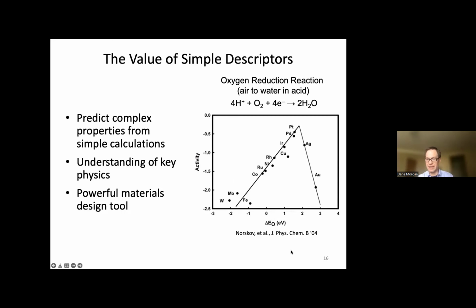So here, for example, is a classic descriptor approach that was pioneered by Jens Norskov about 20 years ago, where he and collaborators looked at the activity of catalyzing the oxygen reduction reaction. So that's combining hydrogen with oxygen to make water, another important fuel cell reaction. And they looked at a measure of the activity that might be the current at a certain overpotential, something like that. And they simply plotted it as a function of something they could calculate easily, which was the binding energy of oxygen to the surface of the metal. And what they found is they got this very nice volcano plot, it's called, where they could get quite a good correlation between the simple quantity and this complicated catalytic reaction. And the power of this is you don't need to fully understand all the steps in the reaction or be able to model them.